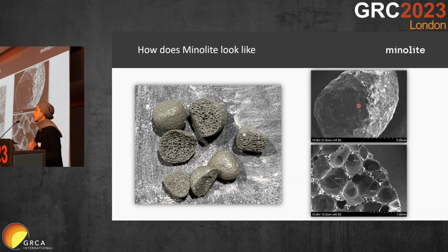If you look at the microscale, you can see that there are some small pores on the surface, and also you can see the rough surface texture. So there are some small pores on the surface, while if you look at the cross section, you can see larger pores inside. These pores are mostly closed and separated.